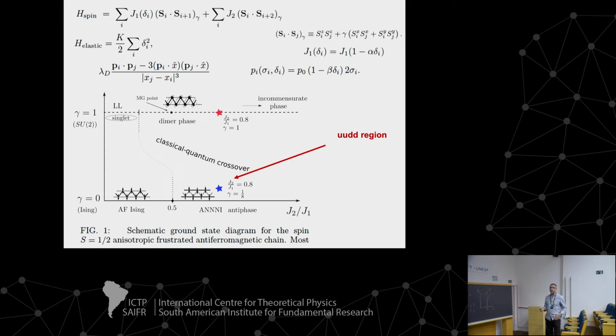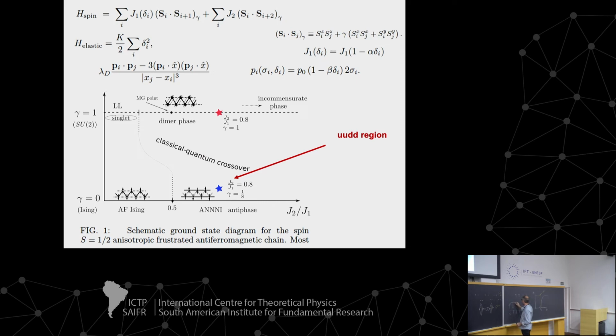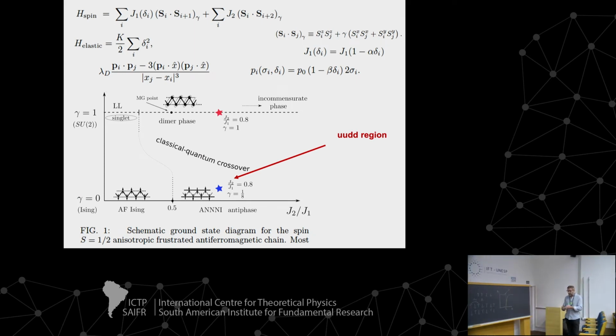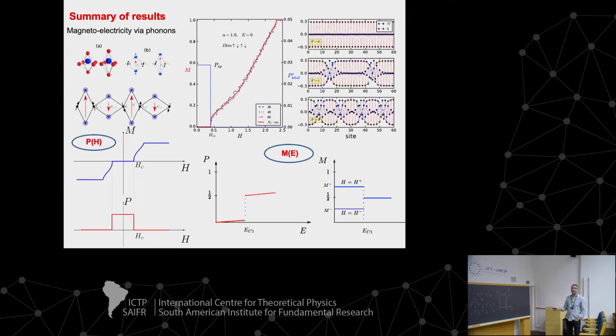So now we wanted to go closer to experiments to reproduce this structure. And as everybody knows, this structure appears if you put second neighbors in some situations. So we added that J2, that is second neighbor interaction. And we also added this non-isotropy along Z. So the two new parameters are a coupling J2 and the coupling delta that gives more weight to the SZ-SZ interaction. And in this region, which corresponds to delta large, so mostly Ising spins, and J2 over some value, this is kind of antiphase. So essentially here you recover this magnetic ordering, and all the rest that I discussed before remains unchanged, okay?